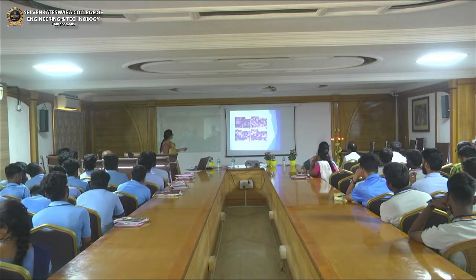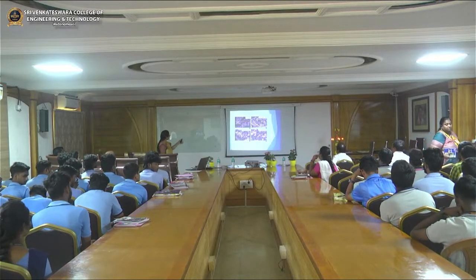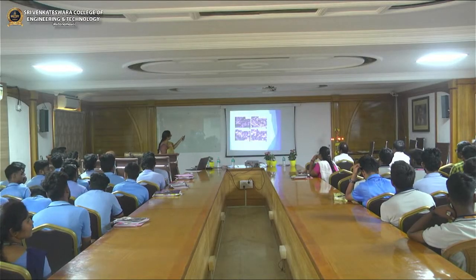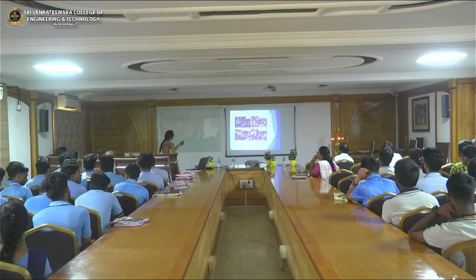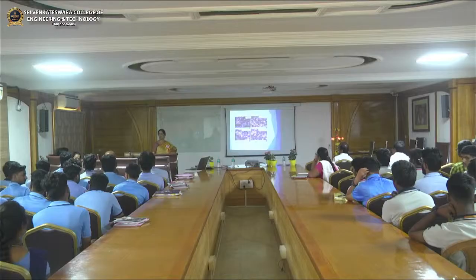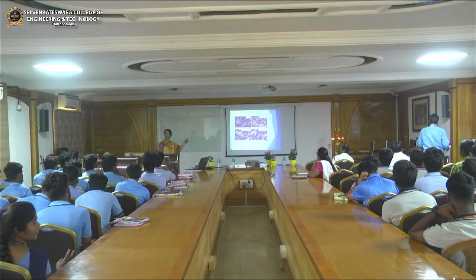When you observe these four morphological studies of the cadmium sulfide, without any capping agent all the particles are agglomerated. As soon as you add PEG, the agglomeration decreases, which means that with PEG the particle size is very limited. When you observe EDTA and PVP, the particle size is very large. So depending upon the requirement, we can choose the capping agent. Which capping agent gives the required particle size is also important.